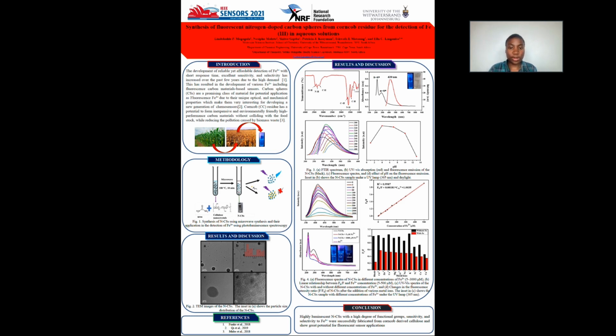Therefore, we can conclude that highly luminescent nitrogen-doped carbon spheres with a high degree of functional group sensitivity and selectivity towards iron 3+ detection were successfully fabricated from corncob-derived cellulose.